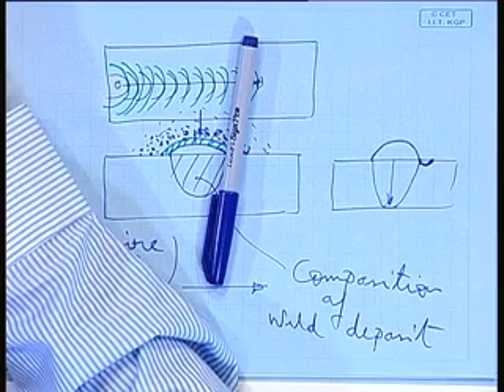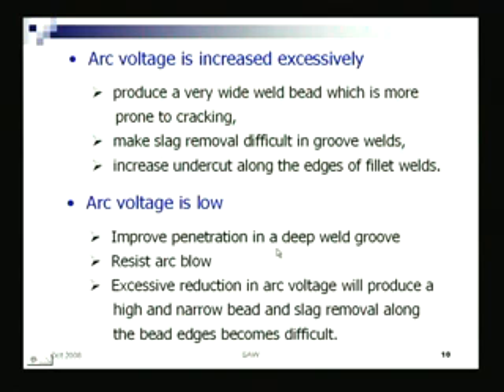If the arc voltage is too low, that means the distance between the electrode tip and the job is too low. It gives improved penetration in a deep weld groove. It increases penetration, and it resists arc blow.